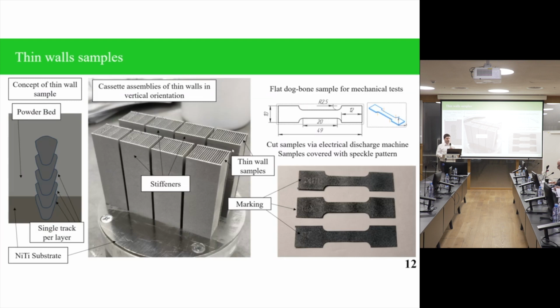And for the second step, thin-walled samples were manufactured. I want to spare a couple of words on the concept of thin-walled samples. The basic idea behind it is to exclude the influence of the hatch spacing parameter, to exclude the influence of the adjacent tracks. So here, for a single sample, we have only 1 laser passage per layer, as shown schematically here. All samples were placed between 2 stiffeners to exclude any possible distortion during 3D printing. And after the manufacturing, these samples in turn were cut by electrical discharge machine to receive the samples for further mechanical tests.